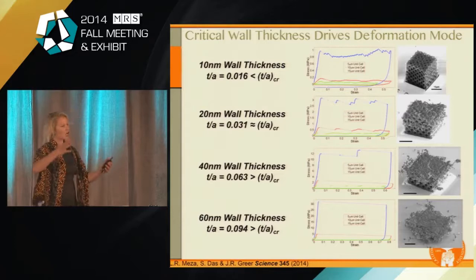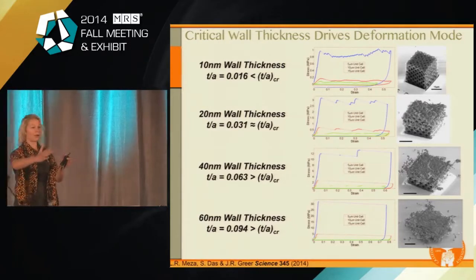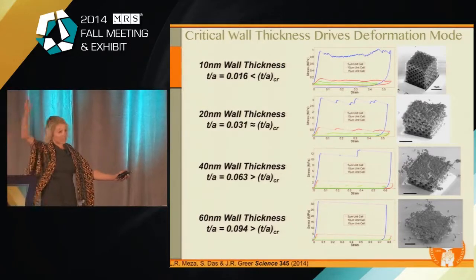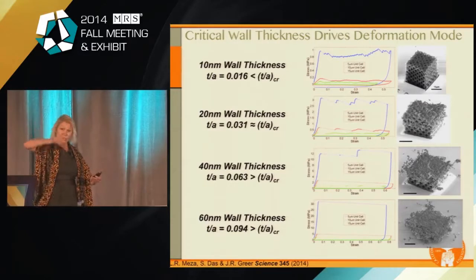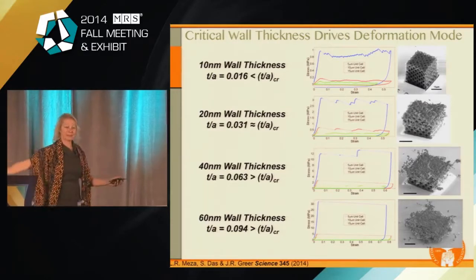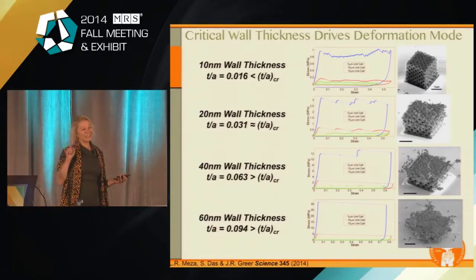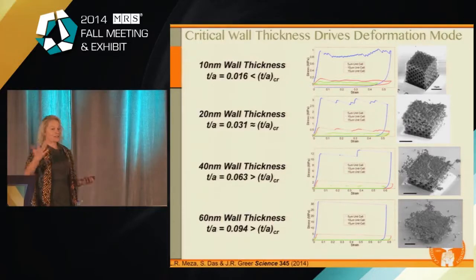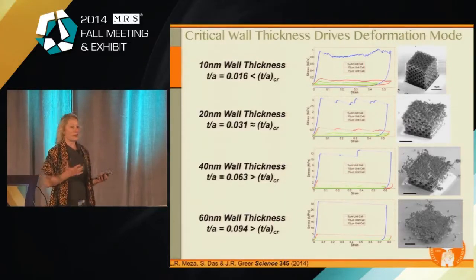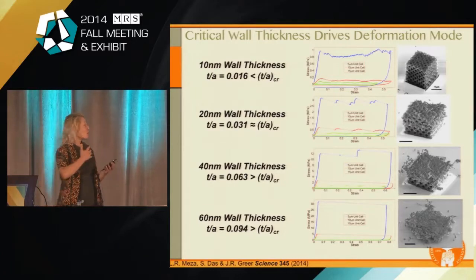Can you imagine concrete tubes with 10 centimeter thick walls arranged into a three-dimensional lattice and then compressing it and actually shell buckling and recovering? That would never happen. So how does size effect manifest itself here? It's not in strength. The reason why this would never happen in a larger structure is because brittle materials fail at the flaws. And we can't make ceramics that don't contain flaws.